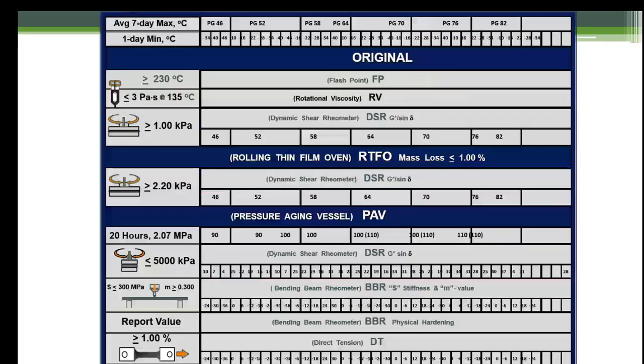This is just the layout. You don't have to memorize this. It's kind of the range of testing based on PG grade. You still got the flash point, but you're using rotational viscosity, and then DSR was the big one, dynamic shear rheometer. It's a G star sine theta test, but we do that both for the initial asphalt, the original asphalt, but also artificially age it and test it and run it again, and it has to meet those specifications. So we account for that aging property as well.